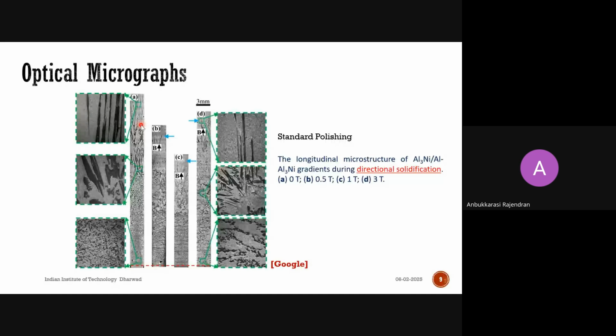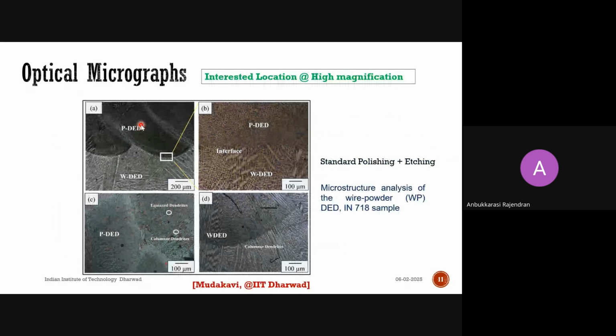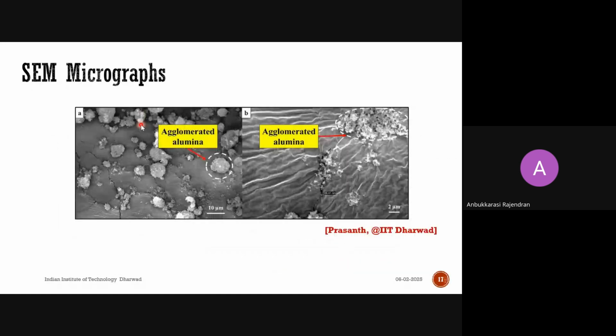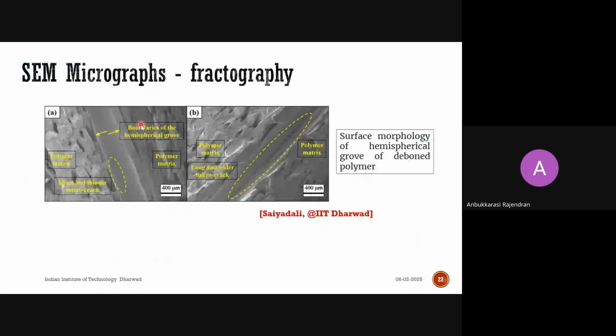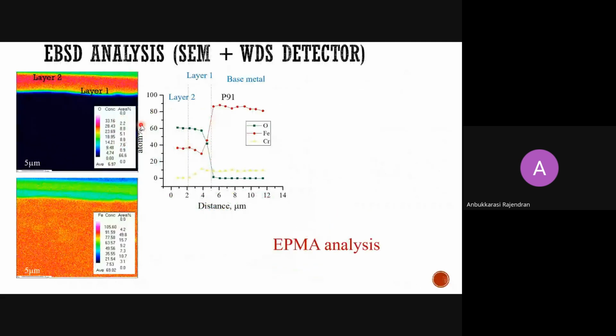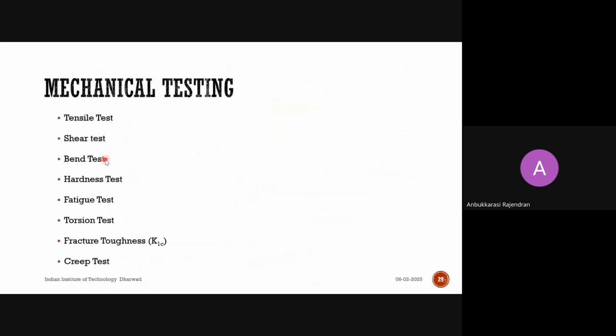Bend test, if you try to bend it. And whether I have included the compression test, let me check. If you do a compression test, prepare a block, try to keep your interface at the middle, then apply the load from the top. I think compression I need to include, but you might be familiar with the compression test. If the interface is strong enough, there won't be any crack initiation from the interface. Otherwise, the interface will fail. So you can come to know whether you have a strong interface or not. These are the simple things you can do.